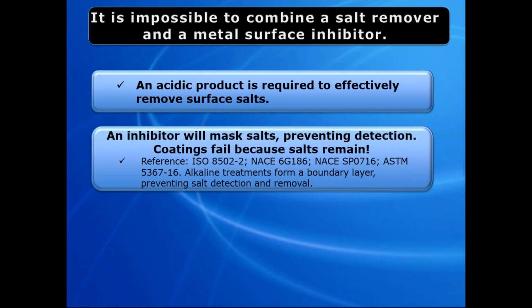NACE SP0716, item 4.2, says a surface inhibitor or passivator. If a surface inhibitor or passivator is used, the test area shall be prepared before testing is performed. For example, by reblasting or wire brushing to remove the barrier layer that can mask any salts. So don't be fooled, ladies and gentlemen. You cannot take an alkaline type product and successfully remove salts. It does require a slightly acidic product to remove salts, in the Chlor*Rid product.